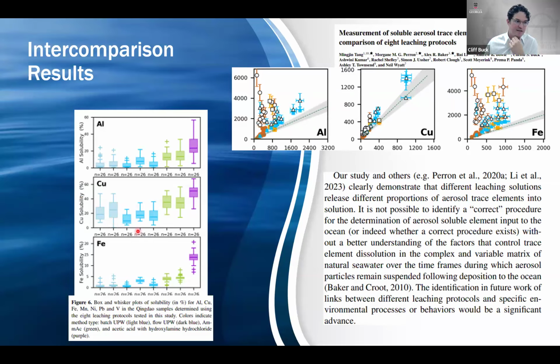On the left here, there are the results of several different methods grouped by their type. In light blue is what we would call a batch ultrapure water leach. In dark blue is a flow-through ultrapure water leach, which I've used through most of my career. Then Alex Baker's ammonium acetate leach, and finally the Berger leach. You can see, depending on what you use, you get different results.